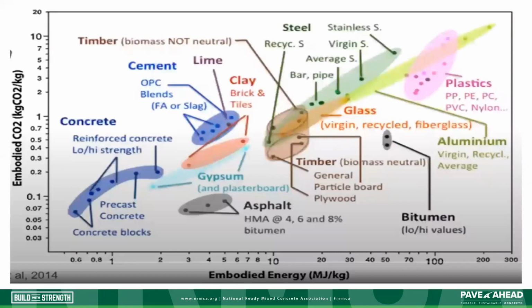So this is a graph that was put together, I believe, by the folks at MIT. And when you look at concrete compared to all the other building materials listed on this graph, you can see that it's a low impact material down in the lower left-hand corner. The chart shows a variety of different materials plotted according to the embodied carbon dioxide on the y-axis associated with producing the materials, and the same thing on the energy scale, which is the x-axis. So that's the amount of energy required to produce that material. It's a log scale increasing by a factor of 10, and concrete and cement are much lower than a vast majority of these materials.